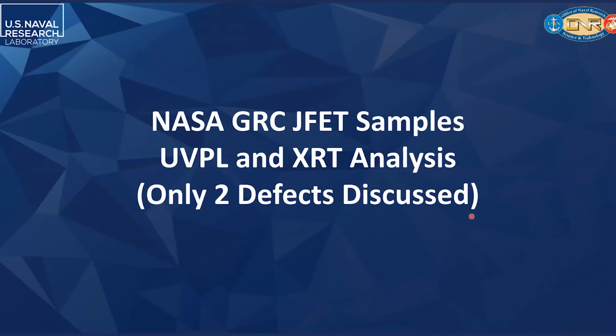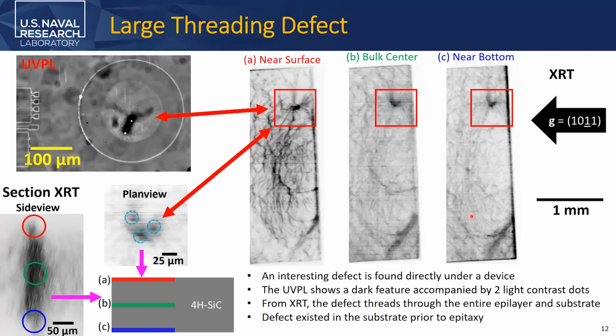They're JFET samples. We did analysis, and I'm going to show you two defects. They're making JFETs because the reliability of JFETs at high temperature operation is much better. So here I can show you this is a device, and we see these defects. We did topography, and from that topography we see these interesting defects right under the device.